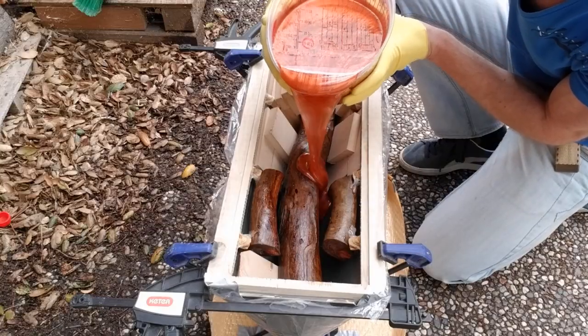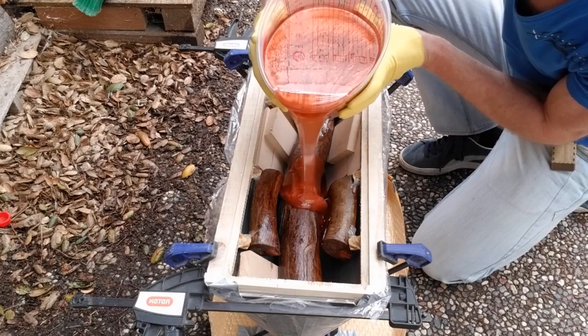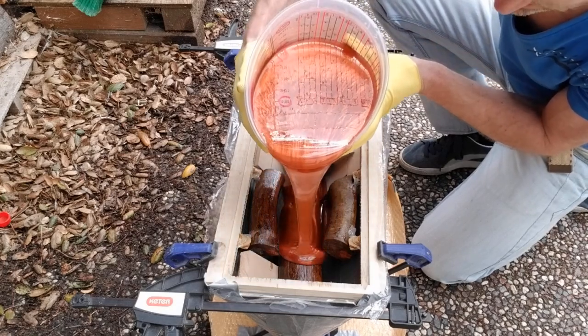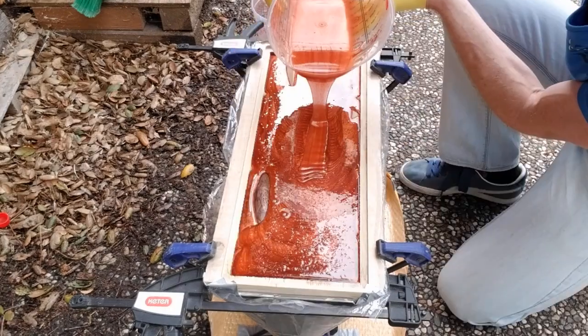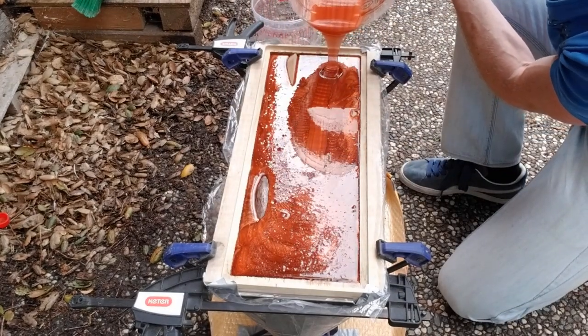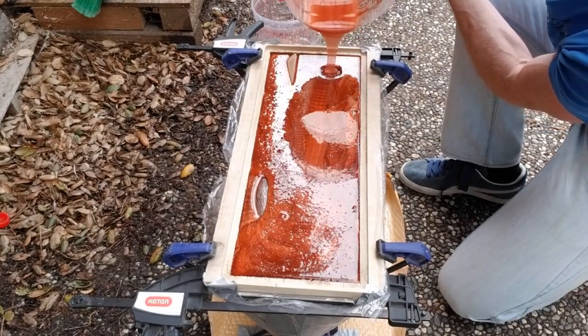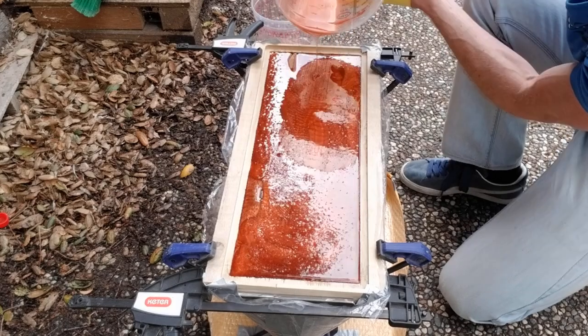I poured both buckets in the mold and let it solidify. With such a large volume, the temperature of the epoxy resin went up quite a bit, and it hardened after a couple of hours already. But I left it untouched for another 2 days to let it completely settle.